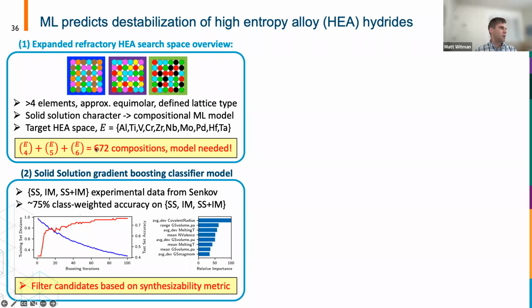We're not just going to assume that all of these high-entropy alloys could actually be made. So we have this phase stability down selection step, where we look at this tabulated experimental data from the Senkov review, where he's gone through hundreds of examples in the literature and classified whether a given composition can form a solid solution, whether it decomposes into intermetallic phases, or is some impure mixture of the two. If you just use a simple gradient boosting classifier model, you can get around 75% class weighted accuracy on this prediction task. And so we're only going to consider materials where this model predicts that a solid solution can indeed be formed.